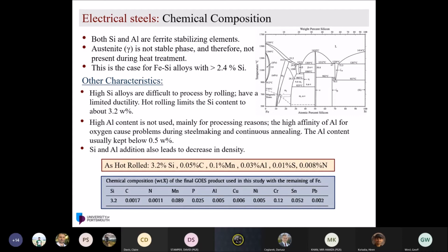And in addition to that problem, aluminum has a very high affinity to oxygen, causing extra problems during steel making and continuous annealing. That's why we always keep the aluminum below 0.5.